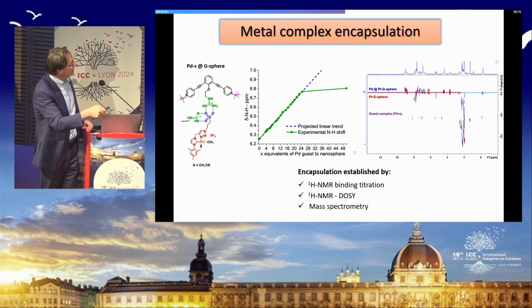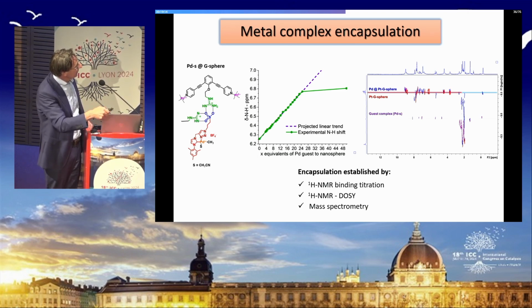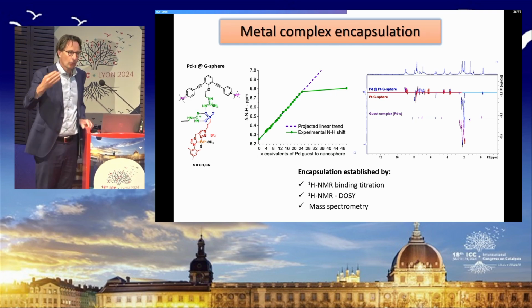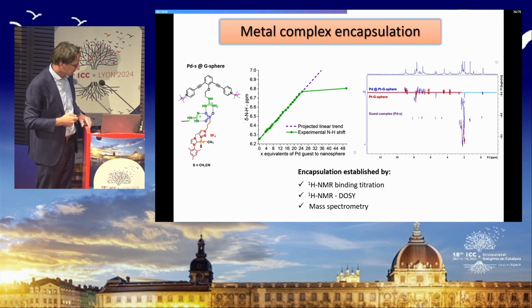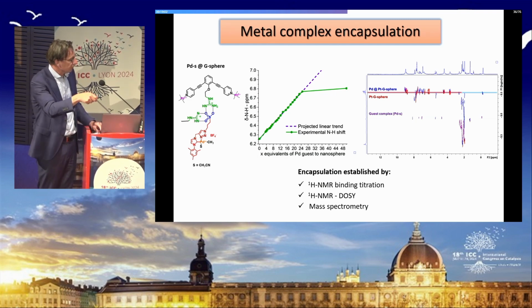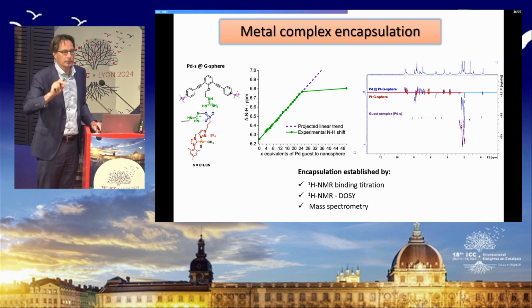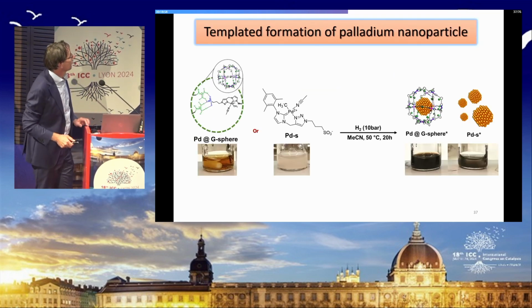And these are the DOSY spectra, so this is the diffusion constant of the free guest complex, and in the nanosphere it overlaps with that of the nanosphere, indicating that all the guest molecules are inside. And again, we also have mass spec data to confirm that these complexes go in.